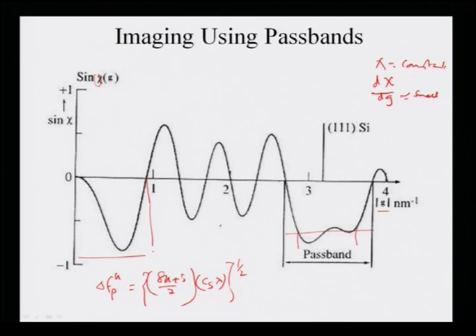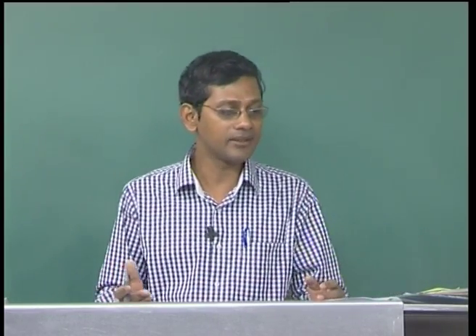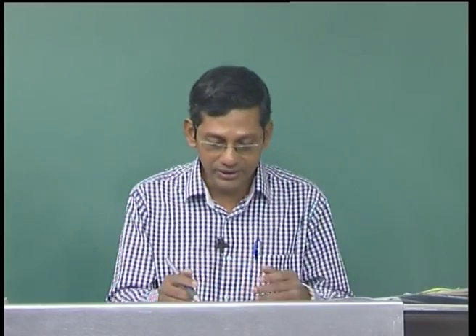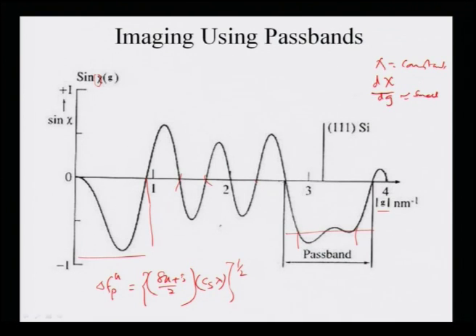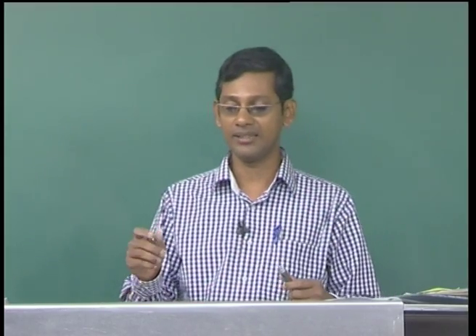So, this technique gives you access to the higher spatial frequencies, thus the finer details in real space. As I said, a higher value of g means finer details in real space. The only price we pay is that now there are many zeros, 1, 2, 3, 4, 5 extra zeros other than the first zero. Zeros correspond to no output signal, and more zeros at lower spatial frequencies means less information transfer, so the transfer function will be heavily affected. That is the only problem, but this is used widely to select the focus in high resolution electron images in many microscopes.